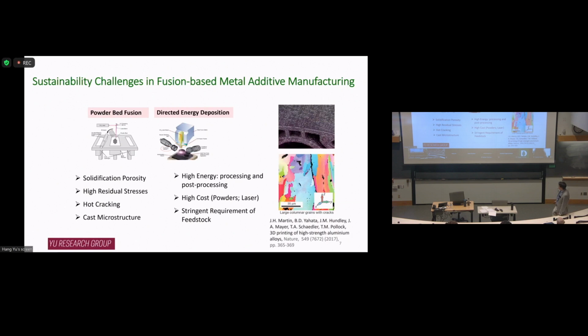And also, if your material is not perfect and you have porosity there, you have to do post-processing, like sintering or hot isostatic pressing, to make it fully dense, right? And the cost is high: the powder is expensive, the laser is expensive. And if you want high-quality parts, your powder needs to meet very stringent requirements. The powder shape and size distribution need to meet certain requirements. So we wanted to solve some of the problems in the area of sustainability. But now fusion-based additive seems to give us more challenges, right? Because of high energy and quality concerns. So what do we do?